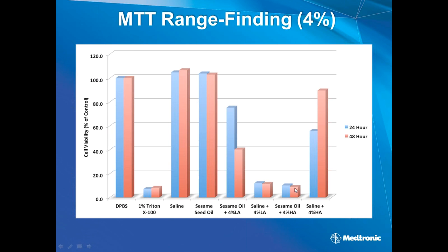And here, heptanoic acid, same story. Heptanoic acid has a relatively high octanol water partition coefficient, so it's more soluble in oil than in water, and that's what we're seeing when you look at these two. Here, heptanoic acid is readily dissolved in the sesame oil, and we have a very high kill rate, only 10% viability of these cells. And here in saline, the heptanoic acid does not dissolve very well. It's more like salad dressing, frankly. So that's why we see a lot higher cell viability in that particular graph.